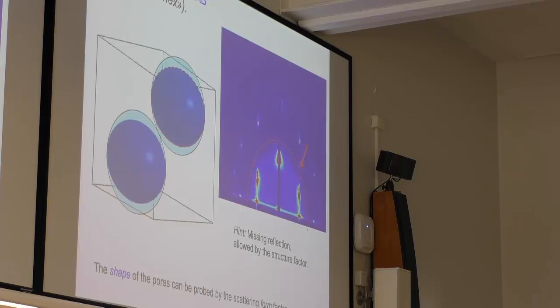Right? So we can really prove from the scattering pattern, and this has been observed previously in calcined films that you look at with electron diffraction, or directly with electron microscopy, you can see that the pores are indeed a bit collapsed in the vertical direction, right? But it's really cute that we can do the same non-destructively in the non-calcined state, right? So one can really see that these micelle structures are already in the thin film phase, non-calcined, a bit deformed in the vertical direction. Yeah. So that was this stuff.